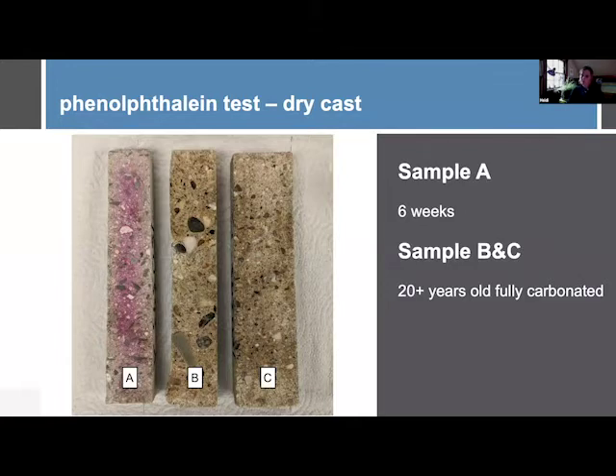So I had a lab perform these tests on 3 different CMU. Sample A is 6 weeks old. Samples B and C are 20-plus years old. Sample B was in our yard, exposed to the environment. I wanted to see if water content would affect sequestration rates. And the one on the right was stored inside for all this time. I think it was part of a shelving unit above the block plant for a very long time, probably much more than 20 years. So the older block is fully carbonated.